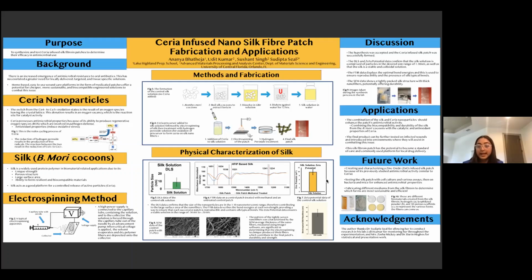And then we see the Zeta potential right here. Again, that's just measuring the surface charge of the silk. We wanted it to reach between -30 to +30 millivolts. And again, that is achieved right here.